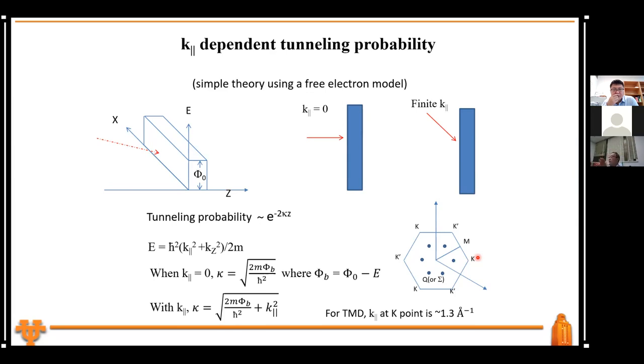And that will give you the state at that K, that Bloch state. But think about it, any other component other than the first Brillouin zone will always add up to outside the first Brillouin zone. So that part of the component makes an even larger K parallel. Right? So you will see that probability drop even lower.